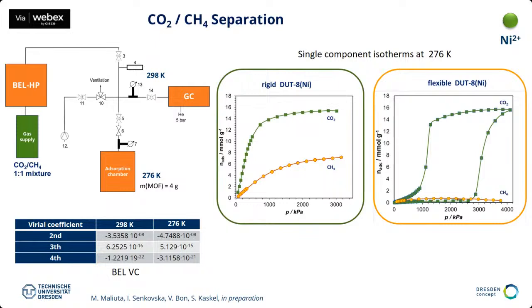And this is very interesting when you compare these nanoparticles with the flexible DUT-8. You see that the nanoparticles have some selectivity for CO2, so they take up CO2 more easily and more CO2 than compared to the methane, because the interaction with the CO2 is higher. But for the flexible MOF, this is completely different. The selectivity is much, much higher, because only the CO2 can open the pores, while the methane cannot open the pores at all. So for methane, the gas is not strong enough to open the pores, and therefore the uptake for methane is very little for this material.